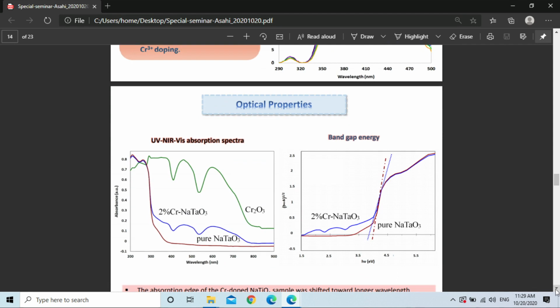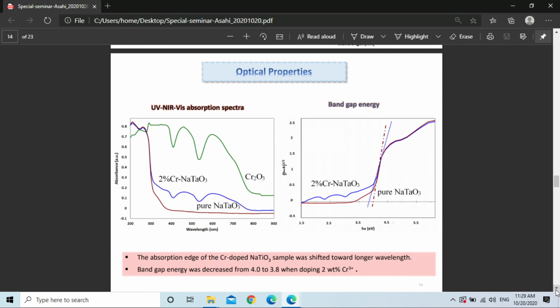We selected the doped and undoped samples to measure the UV-visible absorption spectra, and we can see clearly that for pure sodium tantalate, the absorption edge is about 300 nm. When we dope with chromium, the absorption edge slightly shifts to longer wavelength, and there is some characteristic from chromium and tantalum electronic charge transfer. We can also see the band gap energy when we dope with chromium 2%. The band gap energy slightly decreased from 4 to 3.8 eV. But anyhow, this band gap energy is still wide for use under visible light.